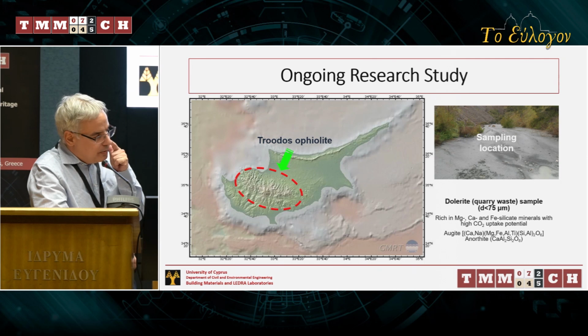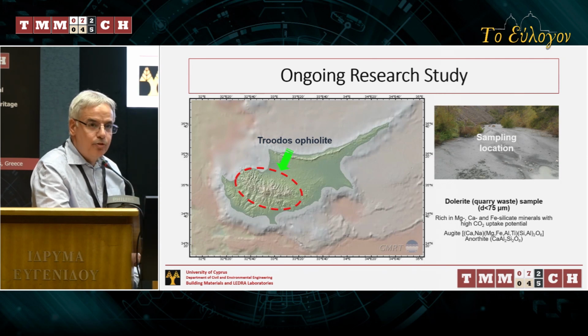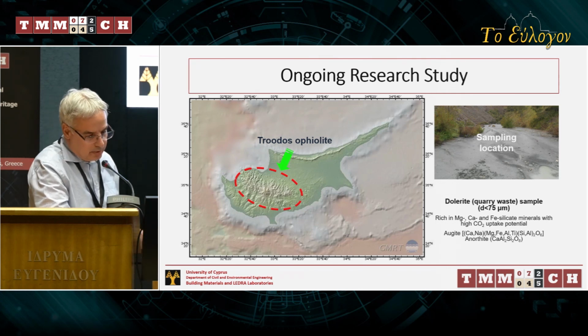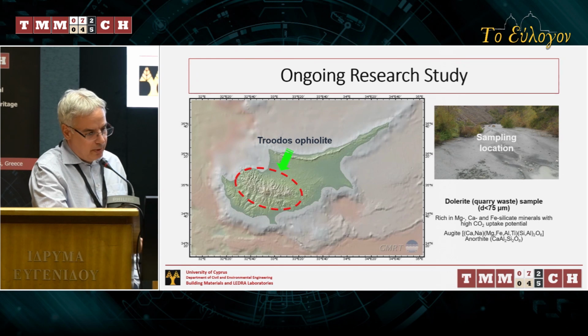In Cyprus, we find these materials in the Troodos-ophiolite region. Of course, what we usually do is we look for the aggregate quarries which are located at the outskirts of the Troodos-ophiolite, and it is from one of these quarries that we obtained one of our samples recently, a quarry waste material with particle size below 75 microns and with the right mineralogy, including minerals which were rich in magnesium, calcium, and iron silicate, suitable for sequestering CO2. These were minerals like augite and anorthite.